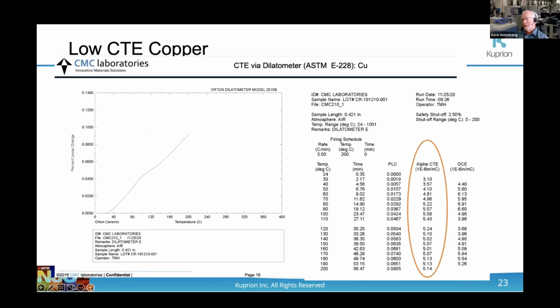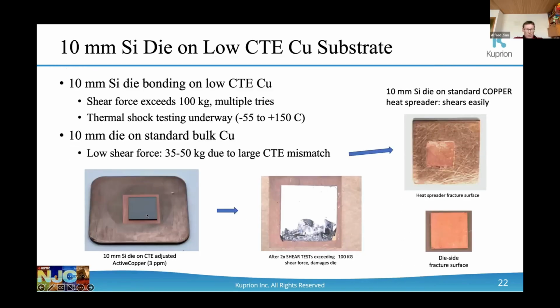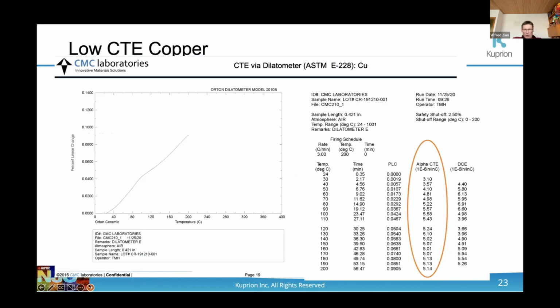And do you have to do anything special with the surface to treat it before applying your ink? For these, we just put another paste of our material down as a very thin layer, and then we bond it down. That way we get the maximum shear strength. That's all. Yep. Here we just use CMC Laboratories to measure our materials, and this is the one formulation with 3 ppm CTE at room temperature.